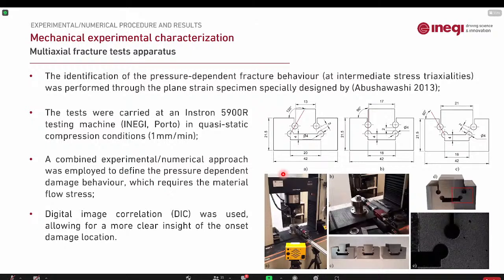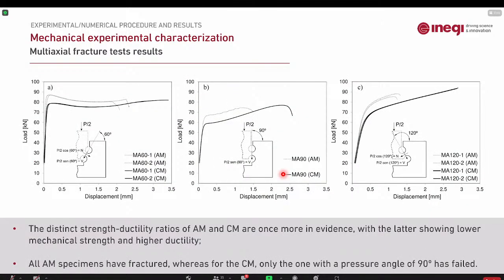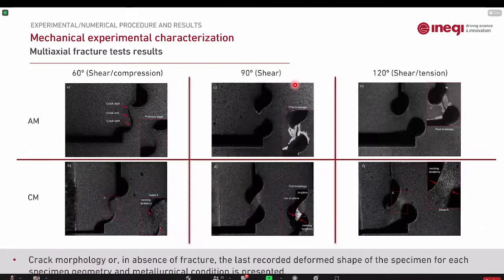And with regards to the multi-axial specimens, we designed notch geometries to test different stress states. With a pressure angle smaller than 90 degrees, we have a mixture of compression and shear. With 90 degrees, it's theoretically pure shear, and larger than 90 degrees, in this case 120, it's tension and shear. So we could characterize different stress states. We did this for additively manufactured and conventional once more, and because of the higher ductility of the conventional, it did not fracture. So we had to stop the test for the conventional steel.